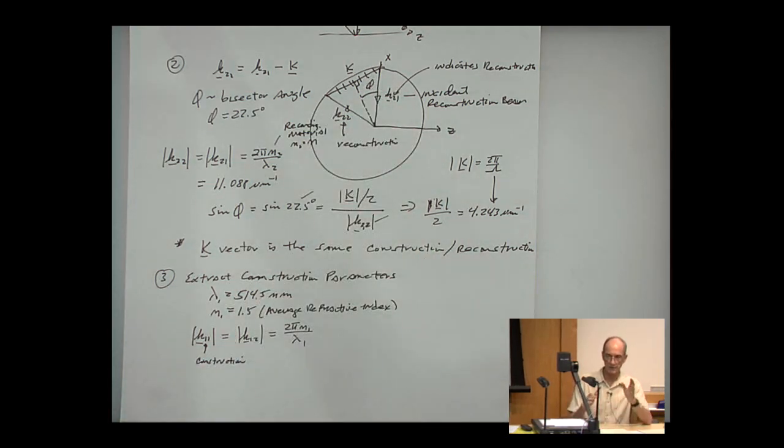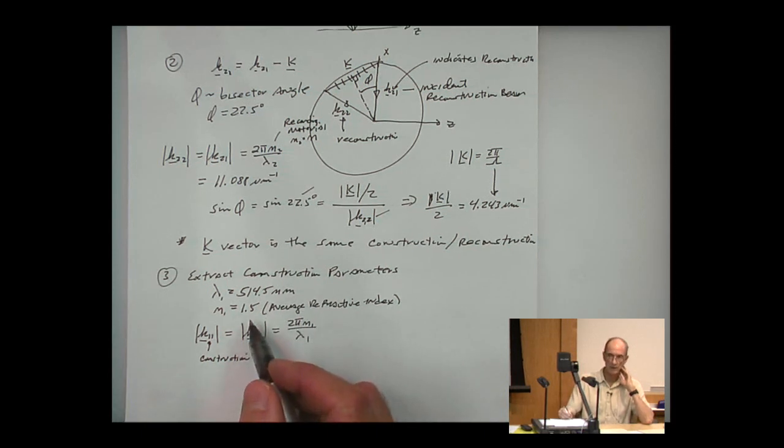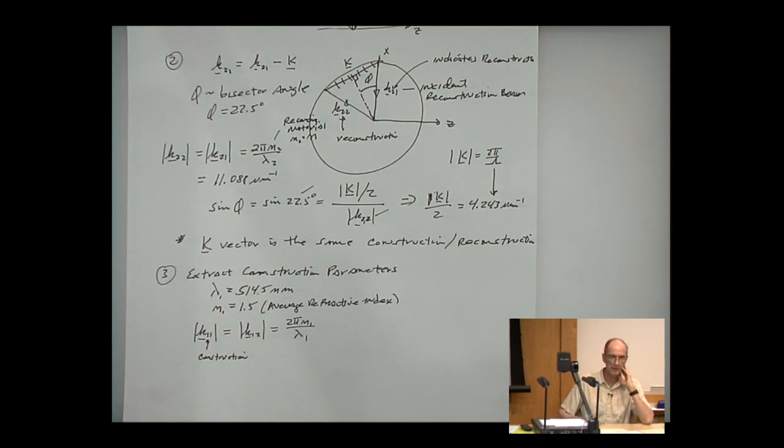And so it could slightly shift, and even more dramatically shift, the reconstruction angle for optimum diffraction efficiency. Okay? So actually, this refractive index could change quite a bit, maybe as much as 0.1, which will cause a pretty significant Bragg shift in the reconstructed hologram.